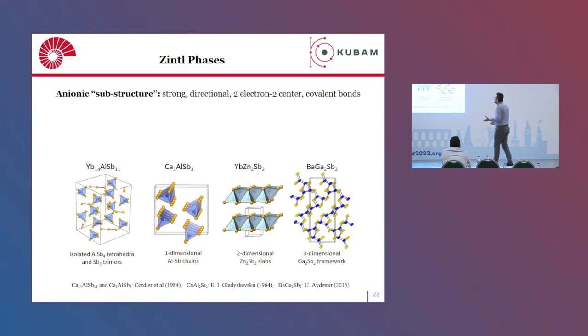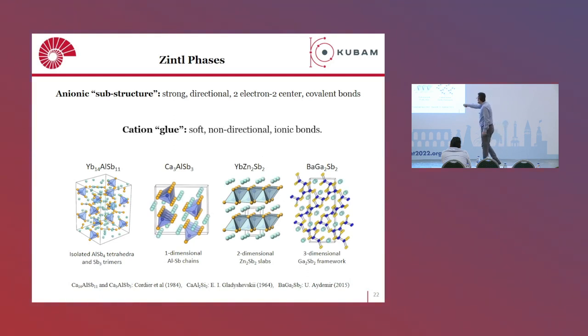Now, these Zintl phases are unique because they have an anionic substructure. You can see here different anionic substructures: 0-dimensional, 1-dimensional, 2-dimensional, layered-like, or even 3-dimensional structures. They have strong directional two-electron, two-center covalent bonds, which accommodate in the cavities, as you can see, these blue atoms, the cations. These cations have soft, non-directional ionic bonds with the covalent framework. So they are kind of like composite materials at the atomic scale.